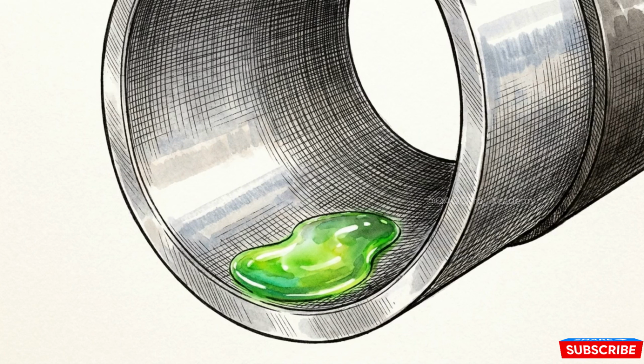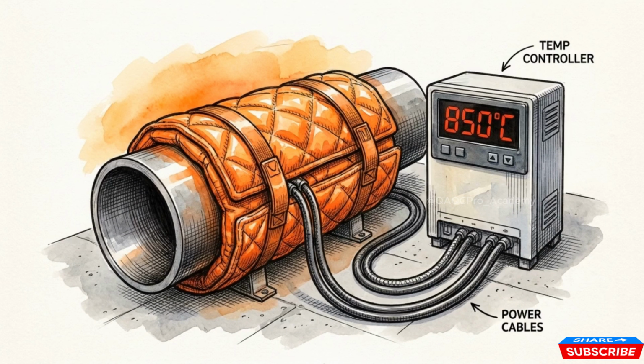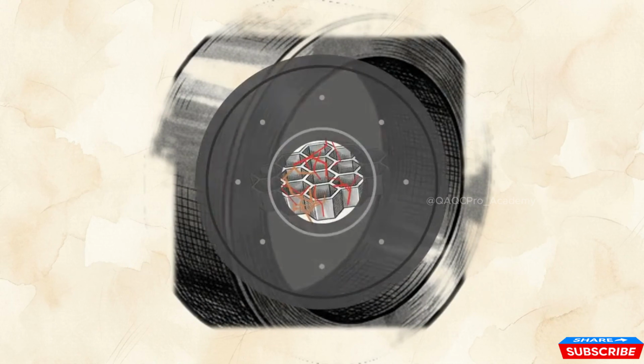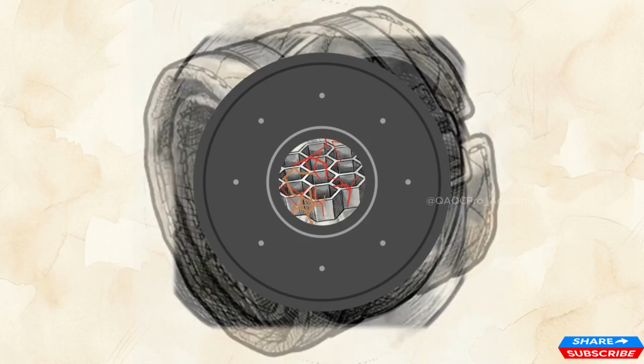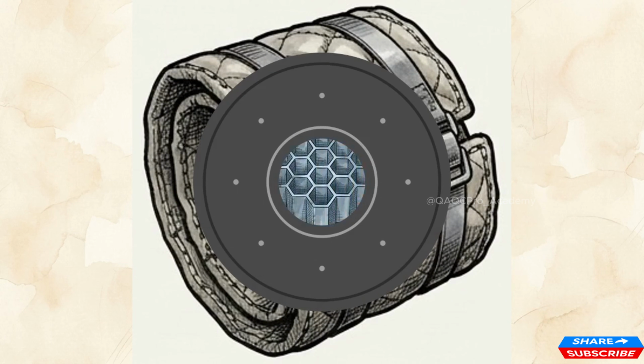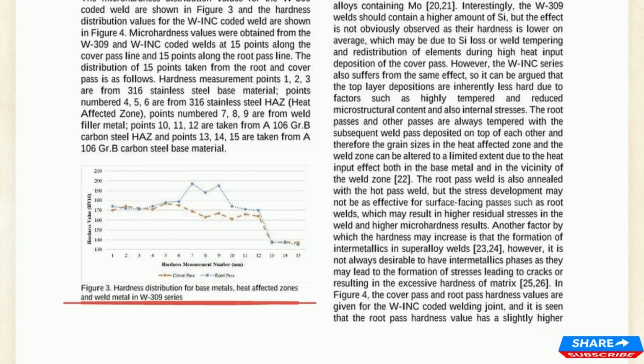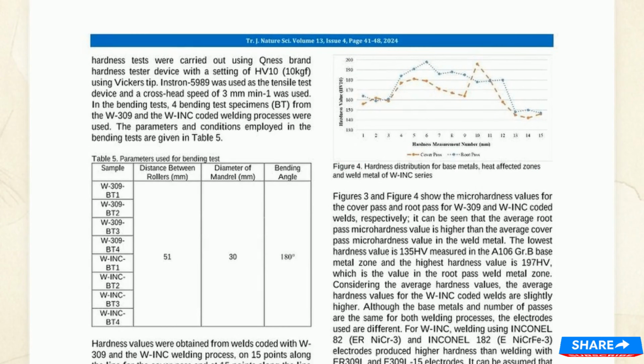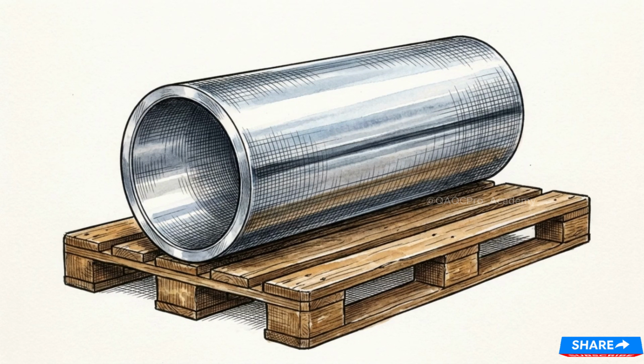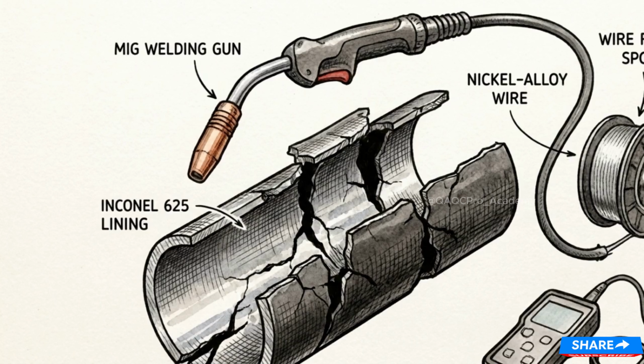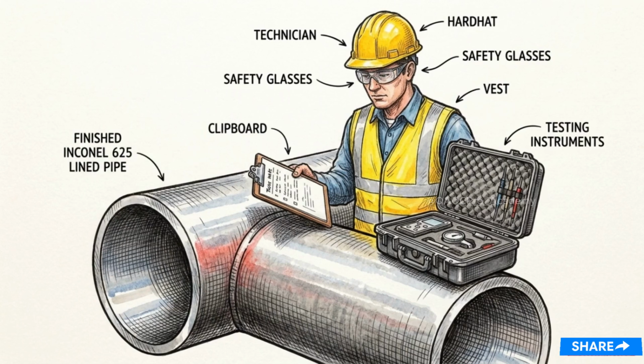After welding, the pipe enters a furnace or is wrapped in thermal blankets, heating to between 600 and 1000 degrees Celsius. This heat cycle addresses the severe internal stresses created by localized cooling of the weld pool. Post-weld heat treatment, or PWHT, allows this molecular tension to relax, stabilizing the bond. This data displays the micro-hardness distribution across the base metal, heat-affected zones, and the weld metal itself. The thermal bake lowers the hardness and significantly improves the overall impact toughness of the cladding. Skipping this thermal phase leaves the pipe looking perfect on the outside, but extremely brittle and likely to crack under operational pressure. The operation concludes with non-destructive testing, which provides the final proof of the weld's integrity.